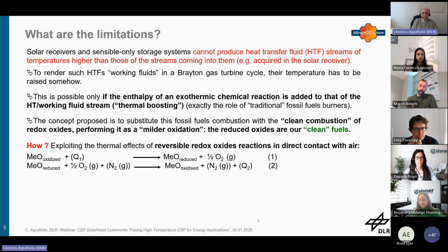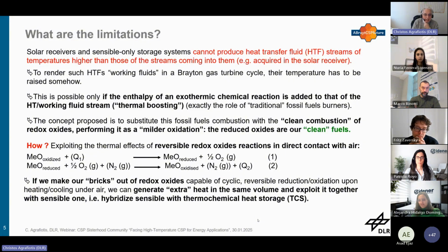Okay, so the idea is that during the day, with the heat coming from the solar plant, one can reduce a redox oxide from its oxidized state to the reduced one by releasing oxygen in the atmosphere. This is an endothermic reaction. And at night, when the sun is not available, one can pass cold air through the reduced oxide to induce this exothermic combustion reaction, regenerate the heat that was spent to reduce the oxide, and get the heat back, reform the oxidized state, and do this in a cyclic process. So the idea is to make these sensible bricks that we showed before, not of inert material, but from a